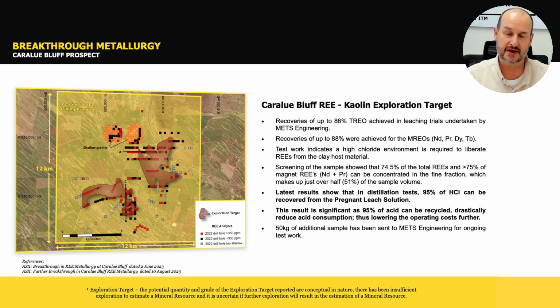So the way that we're addressing that is we've looked to beneficiate those clays, which is part of the normal kaolin beneficiation process. So when we separate out those kaolin clays, we get about 75% of the rare earths going with it, and it reduces the volume by a half. So rather than having to say, in the first instance, if you're processing 100 tons, we only have to treat 50 tons of that rare earth bearing clay, which cuts down the amount of material and therefore the costs that you have to process to get those rare earths off. So that's a major breakthrough in being able to only treat half the amount of material that has a large proportion of the valuable material in it.